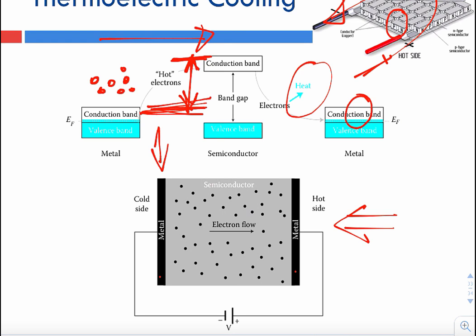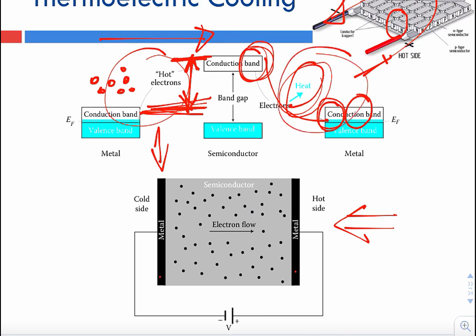We are taking heat from the left metal by accepting only hot electrons into the semiconductor's conduction band, and when each electron transitions back from the semiconductor to the right metal's conduction band, it gives up that excess energy as heat. We are therefore absorbing heat from one side and dumping heat on the other side. This way, we use the lateral motion of the electrons to absorb heat from one side and dump heat on the other. This is the principle of cooling used by electronic refrigerators.